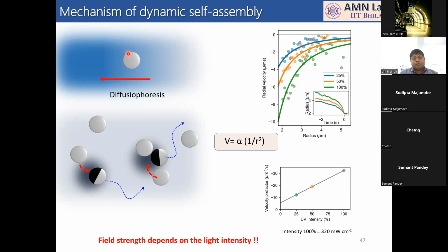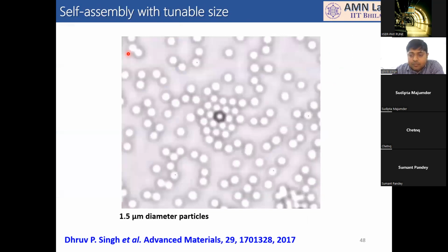So if we have nanoparticles, will they get attached? You mean the assembly will be faster? Yeah. No, it's not that straightforward. If you see the diffusion coefficient of the particle, there is an R in the translational and an R cubed in the denominator of the rotational. So if you reduce the R, the diffusion coefficient also increases significantly, especially the rotational one. So capturing them and keeping them captured might be challenging if you are below 100 nanometers. Above it is fine.